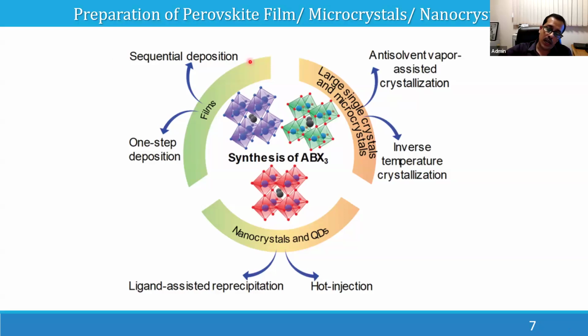So you have one component deposited, like the inorganic precursor. If it is lead, it is lead iodide or lead bromide, you can deposit, and then you can deposit methyl ammonium iodide by drop casting. So together they will react and form the perovskite structure. So that is a sequential deposition. One reagent, and over that the second reagent, and you will get the material, because the entire thing will react on the surface of the substrate.